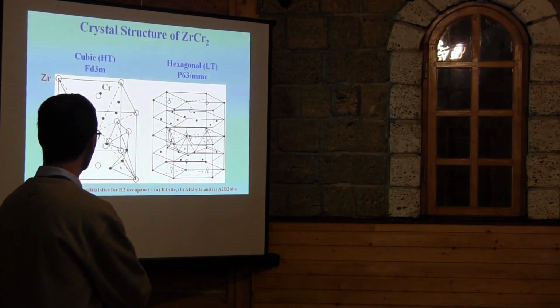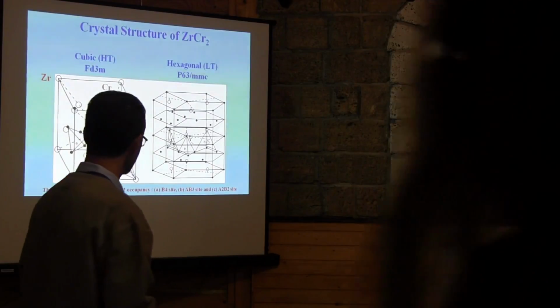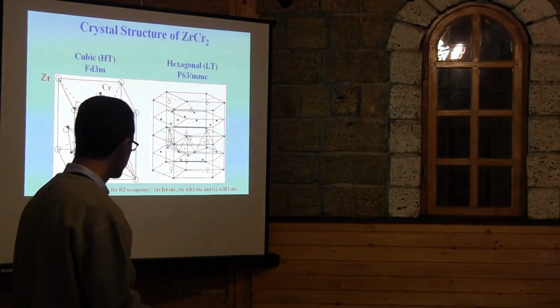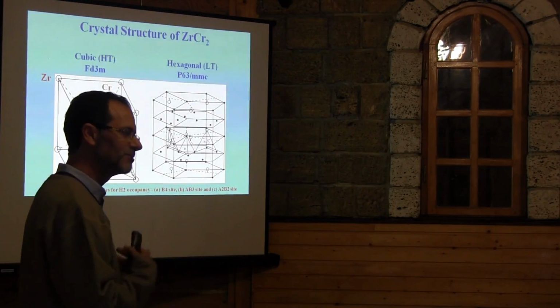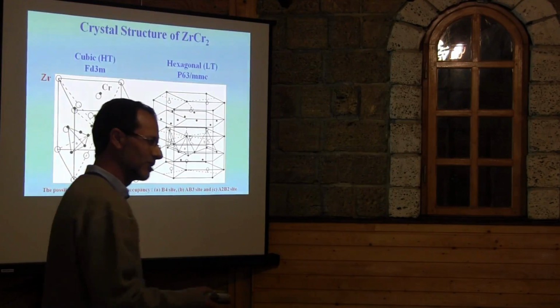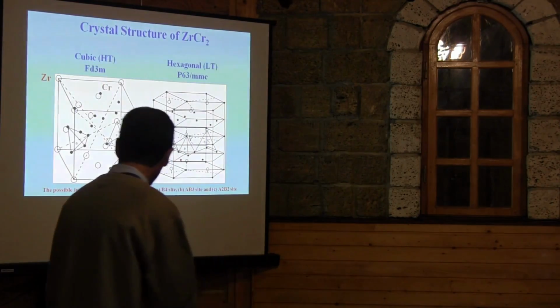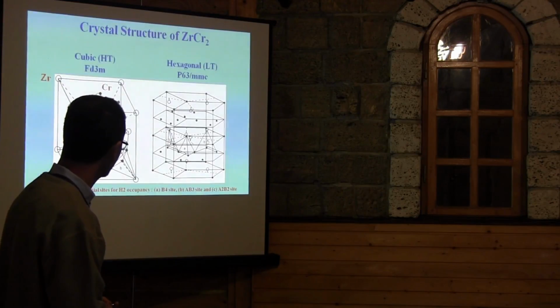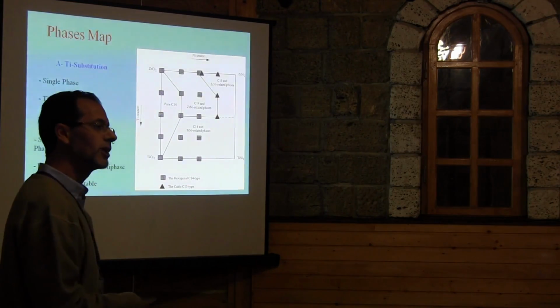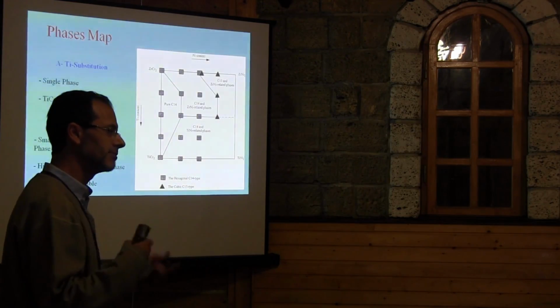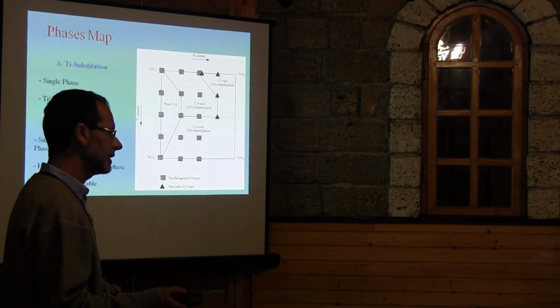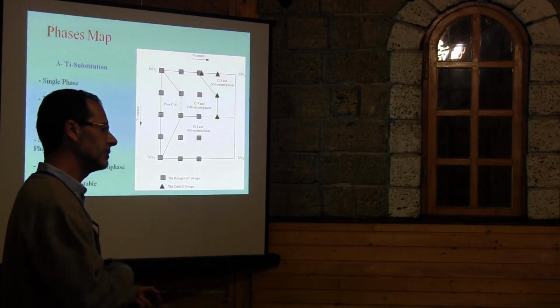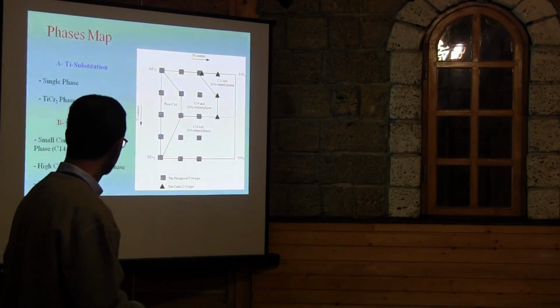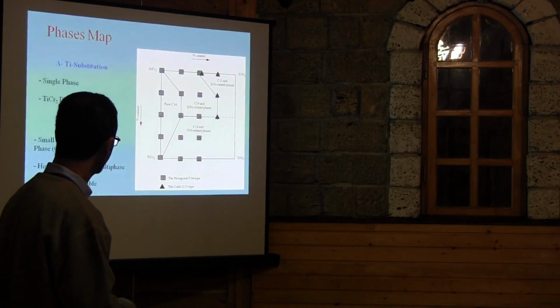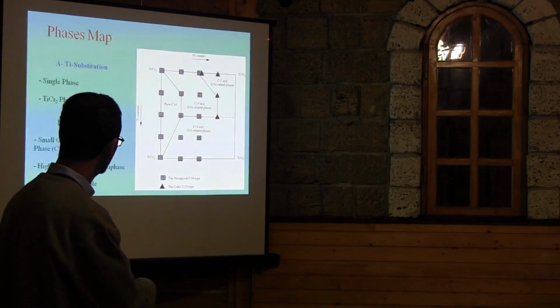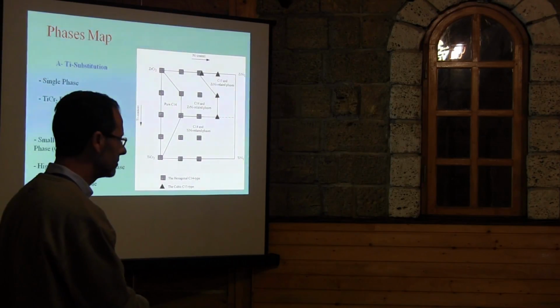You have more sites, and maybe for cubic you have fewer sites. So this is interesting also in terms of crystallography, because I'm a crystallographer by formation. But I don't want to go into details, but if you ask me, I can explain later on. So we made what we call a phase map. Depending on the composition, we can obtain cubic or hexagonal, and we also form secondary phases due to the instability of what we call zirconium chromium 2 and titanium chromium 2.